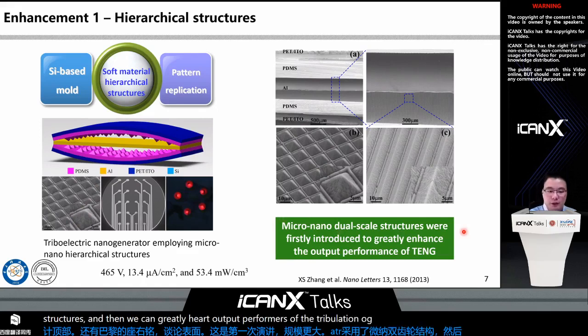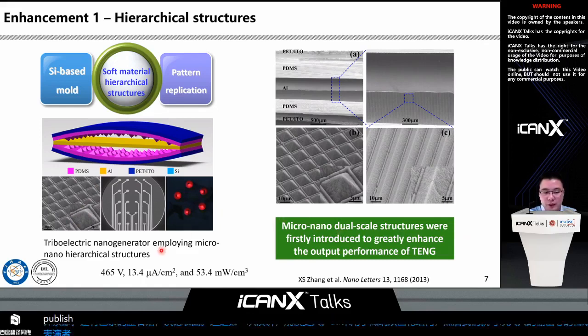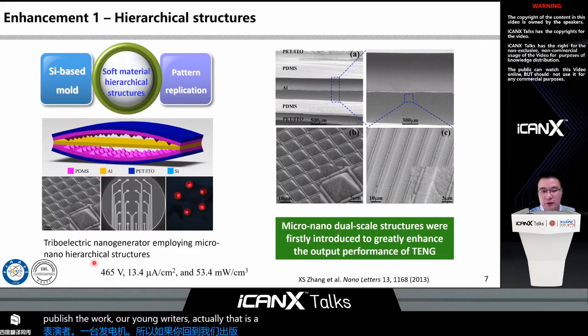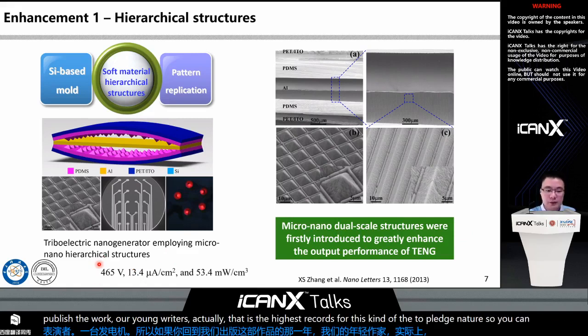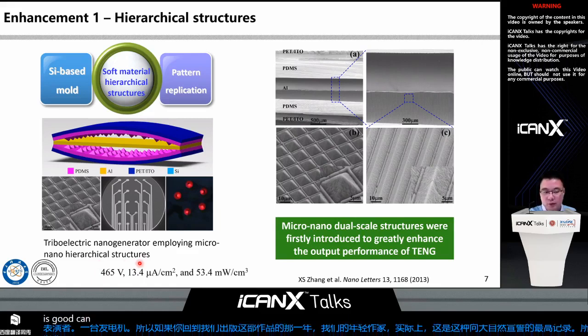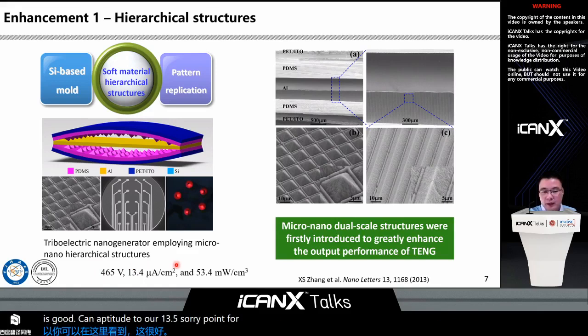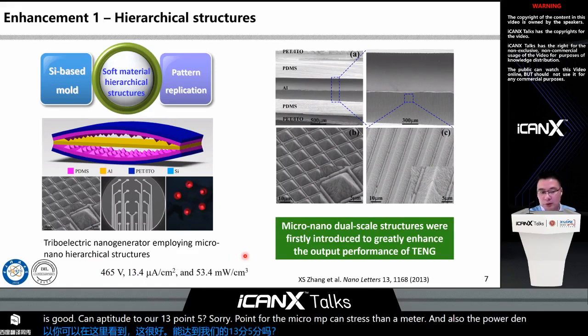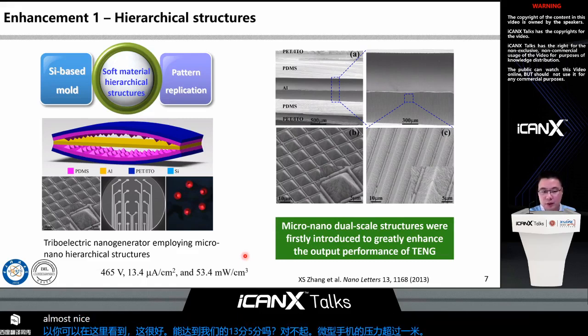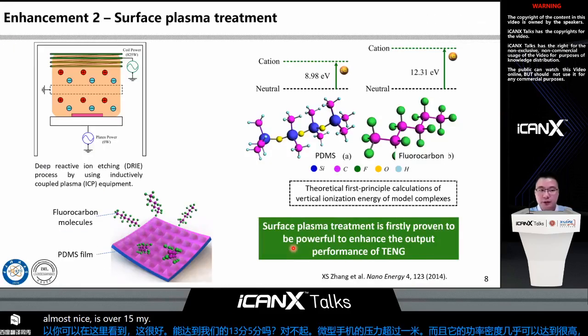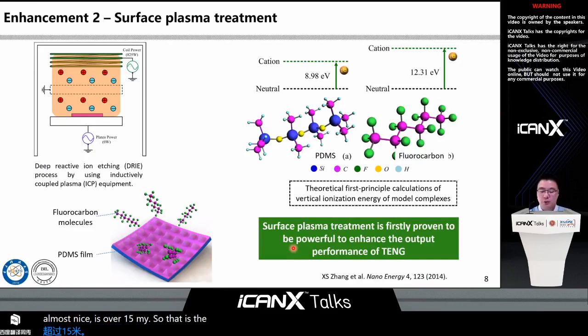So if you go back to the year that we published the work on nanogenerators, actually that was the highest record for this kind of triboelectric nanogenerator. So you can see here that it can achieve 465 volts, and the current density achieved 13.4 microamperes per square centimeter, and also the power density goes up to over 53.4 milliwatts per square centimeter. So that is the work. So that is the first enhancement. The technology we developed is based on surface roughness enhancement using micro-nano fabrication technology.